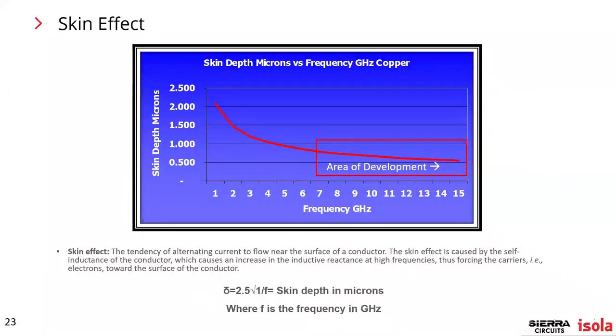Regarding skin effect — if you've done anything in signal integrity, you're aware of how the signal moves to the very outside perimeter of the transmission line. So what's happening at the very surface of the foil matters. Going back to the passivation, silane, barrier coatings, and nodulation — that's where your signal is moving. That's the skin: that very thin layer of copper foil treatments and coatings. For high-speed digital, nickel has been eliminated from the foil treatment process. Also, arsenic is being eliminated — most new foils are now arsenic-free, which is an important attribute.